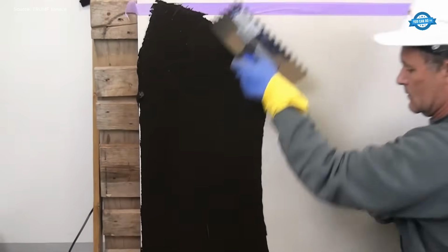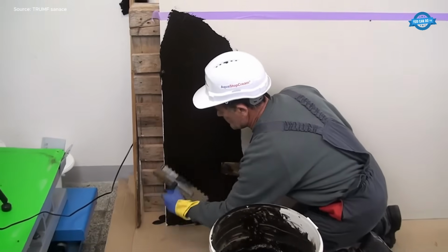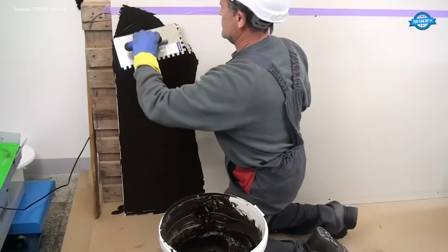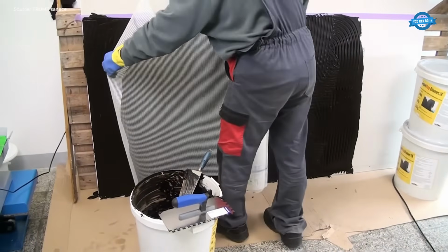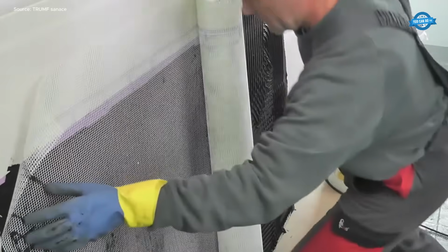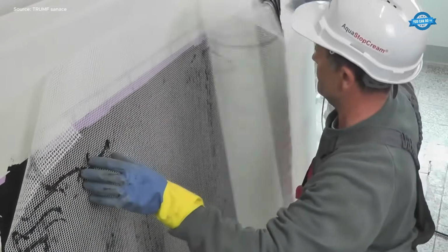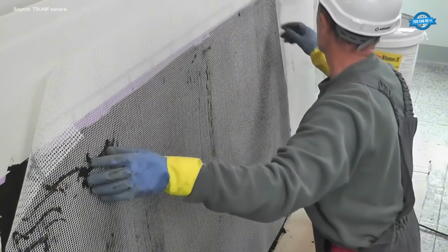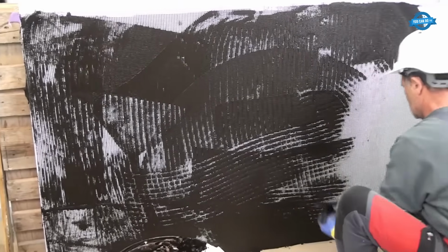Porous or absorbent surfaces are first primed using a diluted version of the same mix. The bitumen paste is then applied using a notched trowel, each layer approximately 1.5 to 3 millimeters thick. The first layer must dry before applying the second. Application should be done in dry conditions above 5 degrees Celsius.